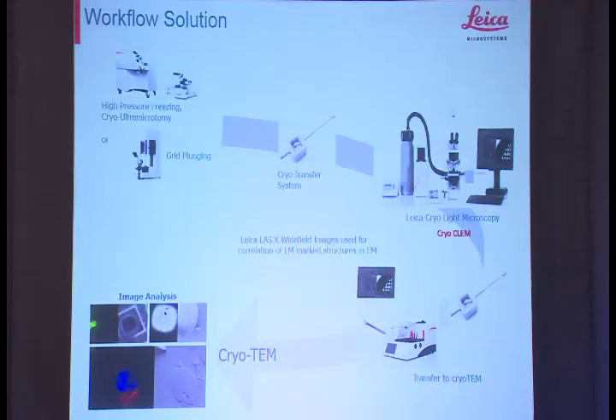So we developed this workflow to allow us to take a sample from freezing through to the light microscope for very quick analysis to find the regions of interest. And then from here, we can take the grid through to a transfer system where we can, with these two little holes here, dock our little cryotransfer system here, and into the other one, we can dock a cryo TEM holder. So you can do a transfer inside here under nitrogen conditions, low temperature, and without any ice contamination, and then off to the cryo TEM.